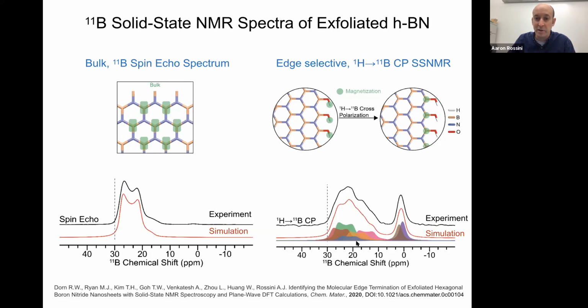These new signals have lower isotropic chemical shifts between 25 and about 12 ppm, and those chemical shifts fit with what you would see for oxidized boron compounds. So if you look at boron oxide or boric acid, that's where these chemical shifts would come in. So these are tentatively assigned to boron atoms that have hydroxyl groups attached, or on the armchair edges where we can have both bridging oxides and hydroxyl groups on the boron atoms. And we have DFT calculations that validate those assignments.